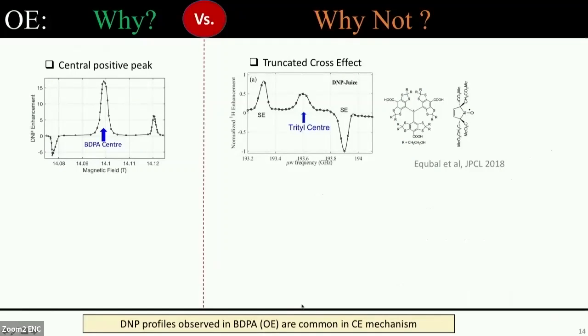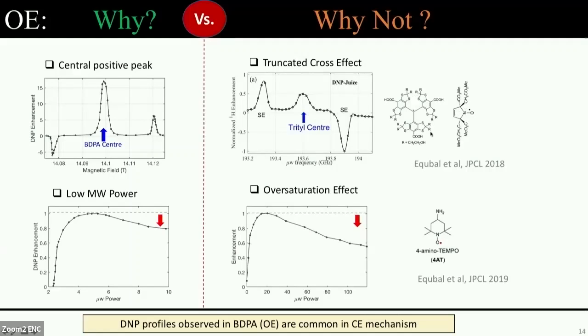These features are very common even for cross-effect DNP. For instance, the central peak that we see here, it's assigned to Overhauser, but this central enhancement is possible even through cross-effect between a slow relaxing and fast relaxing radical. So, for example, a couple of years ago, we found that trityl gives the central DNP enhancement when it is in cross effect with a fast relaxing TEMPO. The other thing is the power requirement. In Overhauser effect, it's thought that the saturation is allowed single quantum transition, so the power requirement is low.